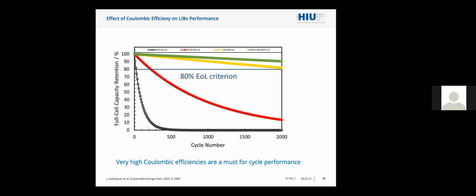This is something that especially young people always have to keep in mind, okay? What I'm plotting here is the life expectation of a cell based on the Coulombic efficiency of the cell itself. Very frequently, this is also a problem for my work as editor. Very frequently I receive manuscripts in which Coulombic efficiencies in the order of 99% are reported. But please always consider that in order to have a decently working lithium-ion cell, or any kind of cell in which the ion is shuttled between two hosts, so there is no reservoir of the metal itself, the Coulombic efficiency, in order to get a decent life, has to be extremely high.